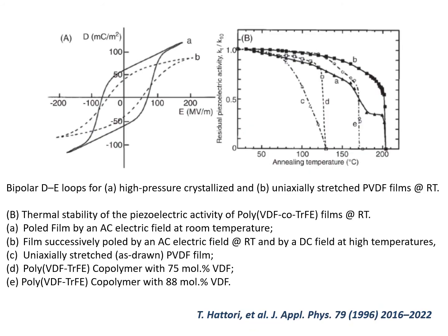At the beginning of my presentation, I mentioned that it was possible to show a different tendency of the polymorphism according to the treatment you use on your film. So this chart represents the DE curve regarding a high pressure crystallized PVDF, which is more of a ferroelectric behavior, and compared to uniaxially stretched PVDF at room temperature. So it can be a little bit slimmer. It's not yet piezoelectric, but it's a much better profile than when you make a high pressure crystallized system.